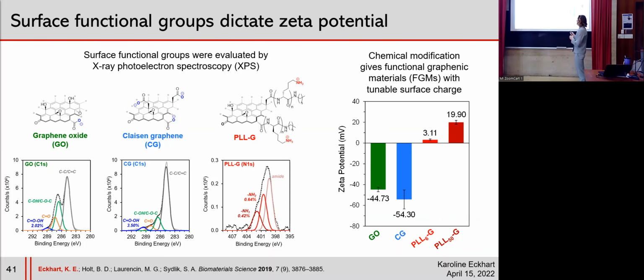We made one with a degree of polymerization of 6 and one with a DP of 50 on the peptide. And we're looking at the high resolution N1S, or the nitrogen here, to identify the presence of ammonium and amine peaks that represent the source of the cationic charge on this material. And we can see that the zeta potential of the PLLGs are both positively charged, and that the magnitude of that positive charge depends on the degree of polymerization of the polylysine, either 6 or 50. And so overall, we established this synthetic pathway that gave us access to a series of FGMs with different controllable surface chemistry and resulting differences in the surface charge.